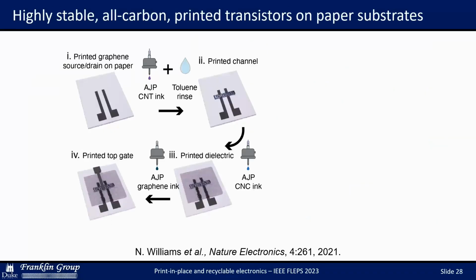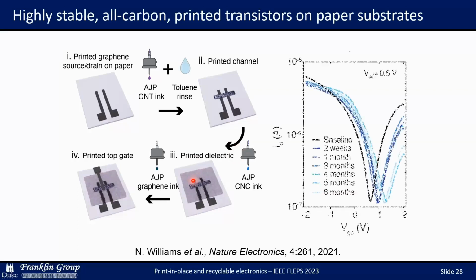And it turns out the dielectric is actually an ionic dielectric. There's enough hydration and charge composition to yield a very high functioning electrolytic dielectric film. And that allows for the transistor to operate at really reasonably low voltages. You can see the sequence of the devices here. You load the paper substrate, print the nanotubes, print, in this case, we use graphene as the source drain and the gate electrodes, and then this crystalline nanocellulose as the dielectric.